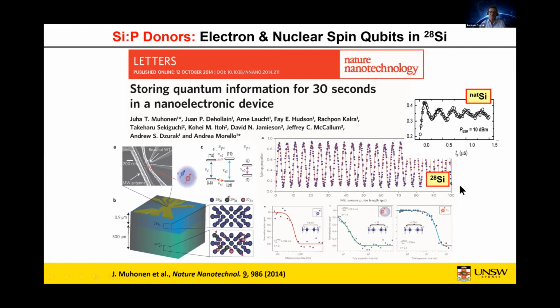In fact, electron spin coherence times are now of order 1 second when one employs dynamical decoupling measurements. And in this silicon-28, the phosphorus nuclear spin was shown to remain coherent for 30 seconds when using dynamical decoupling. So incredibly long coherence times demonstrated. This result really showed that with isotopic enrichment, one can get extremely high fidelity for silicon-based qubits. It was a very, very important result.